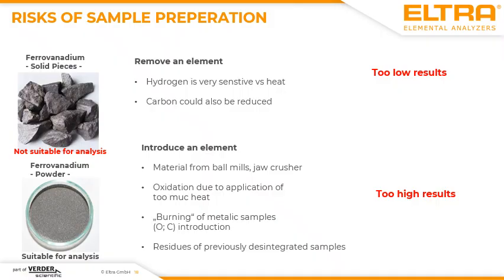and carbon of the sample will be removed from the sample. But it's also possible to falsify the result by introducing an element. For example, when you prepare the sample with a ball mill, it's also possible that you introduce material which comes from the balls inside. It's also possible to cause a big oxidation effect because the heat inside the ball mill is too high, so that you have oxidation of the sample. When you even put more energy in and the sample, for example, starts to burn, it's also possible that you introduce carbon because of the burning process.